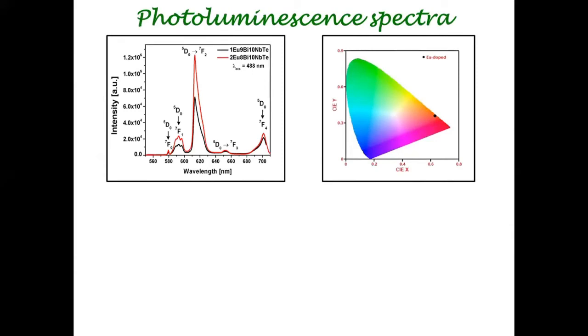This is the PL spectra of europium doped bismuth niobium telluride glass ceramic. And we see very strong emission in the red part of the electromagnetic spectrum, and very little light is emitted below 500 nanometers. So in its chromaticity diagram, the x coordinates are around 0.6 and the y coordinates are around 0.4. So these are very strong red emitters. If you want red phosphors, europium is the candidate.